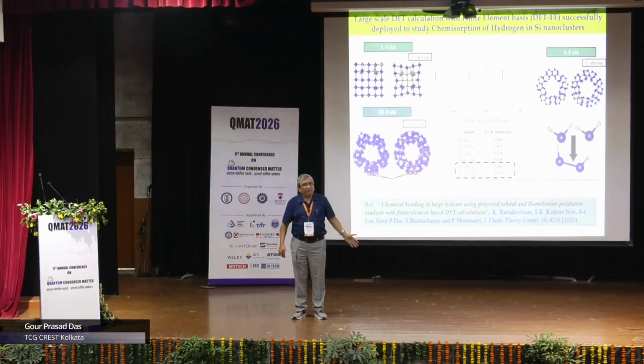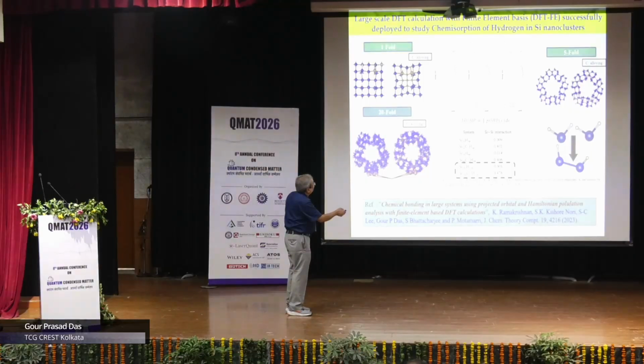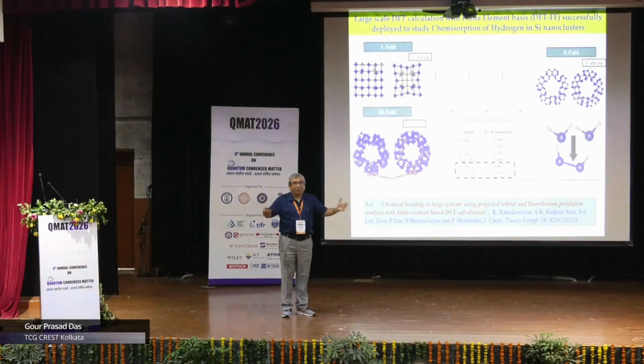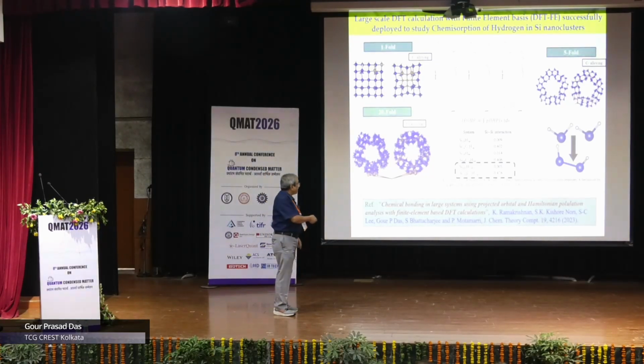We failed. Quantum Espresso could go up to 5-fold, up to 10-fold. But when we went to 20-fold, it just conked off. In the best possible computer in our country, we could not do it. Okay? So, plane wave raises the hand. And there the finite element comes, and we could get that. There are details which are available. Those of you who are interested, you can see that.